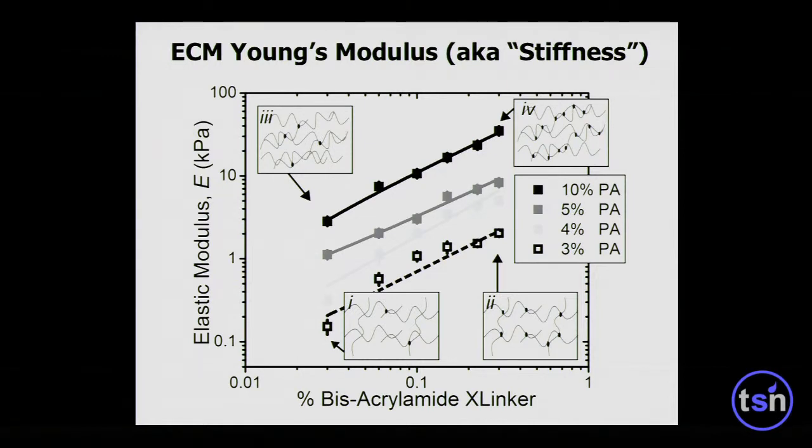But you can also cross-link it together, and I like to think of that as half-cooked pasta, where it sticks together at some points, and as you pull a network like that, all the other noodles translate with the noodle that you've grabbed onto. So you can effectively make the environment stiffer, either through having more bulk in terms of entanglements, or more crosslinks.